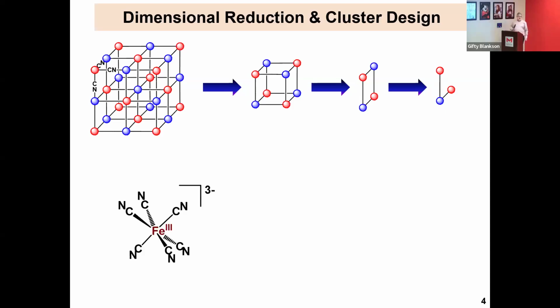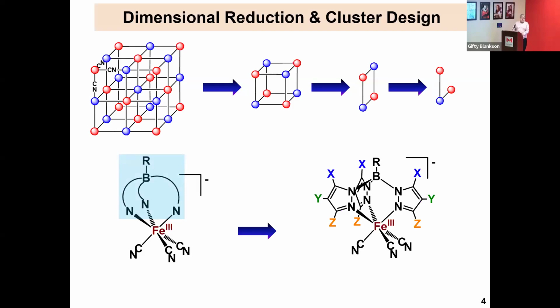So instead of using 6 cyanides around an iron 3 spin center, we decided to simplify the problem, remove 3, and put a tridentate ligand, an organic molecule with a 1- charge, that takes the place of those 3 cyanides. It reduces the overall charge of the complex. And now we have a scaffold in that this ligand can be substituted at up to 10 chemical positions, including the boron and the R group. R could be any alkyl or what have you.